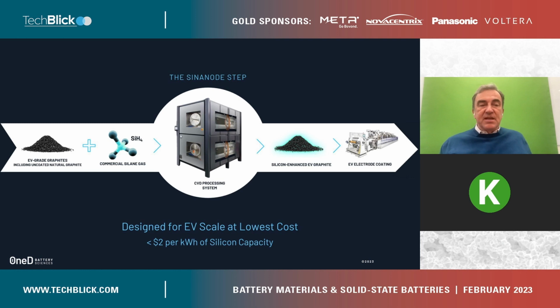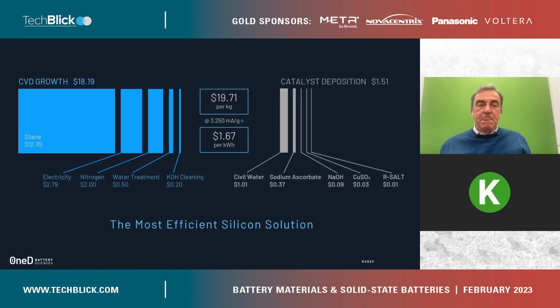So to summarize, the process uses existing graphite and commercial silane, both available in large quantities, and equipment that is available from multiple suppliers, and produces at the end something that is ready to be used. It's a silicon-enhanced graphite ready to be used in all of the existing EV cell factories. And what's unique is that this increases the value of the graphite while decreasing the cost, because at the end of the day, you need less graphite per vehicle. You go, for example, from 60 kilograms of graphite to about 20 kilograms of graphite, because the silicon is providing most of the specific capacity.